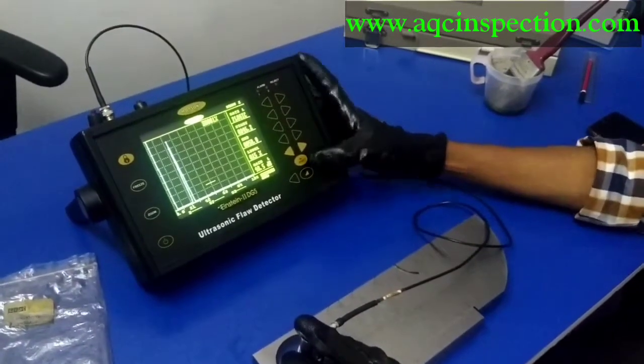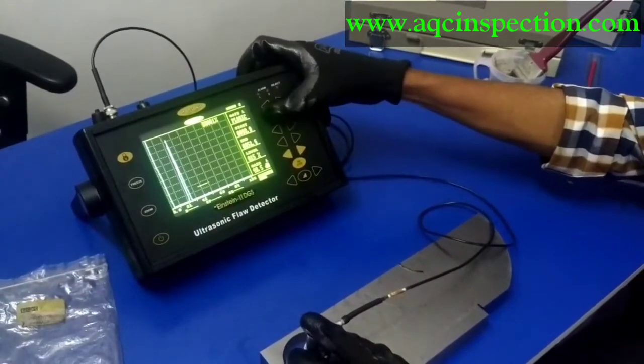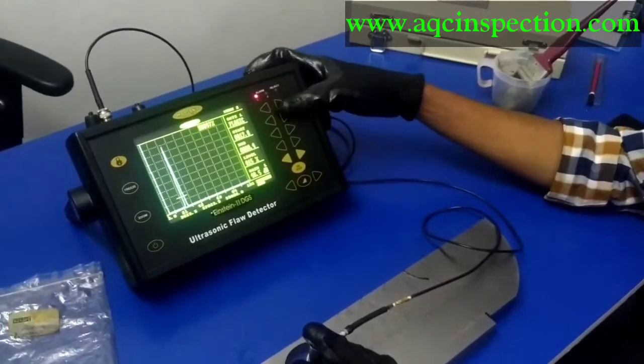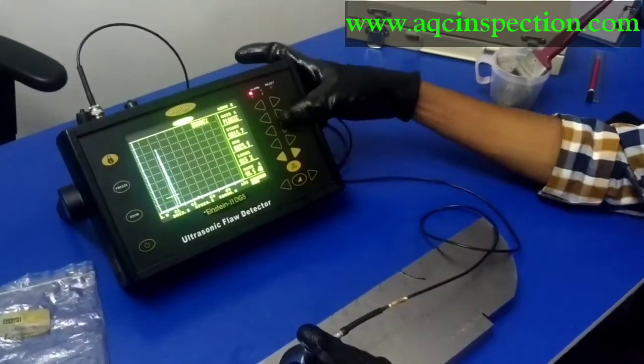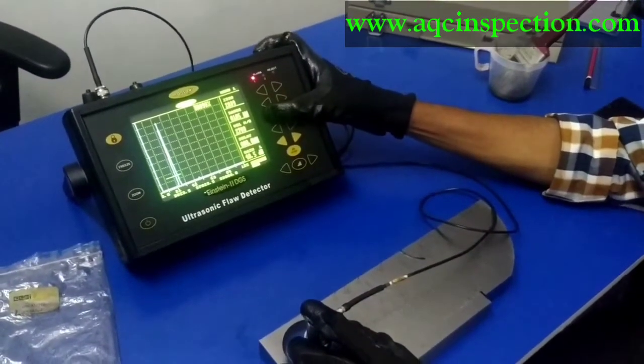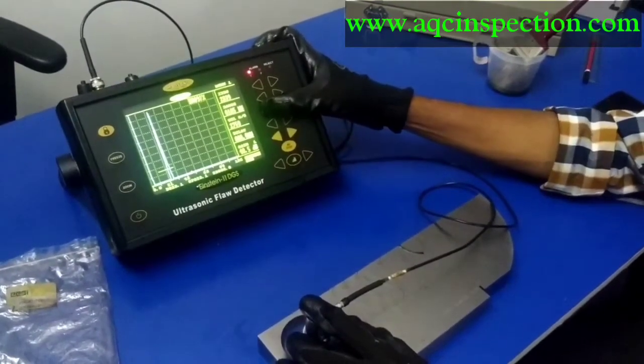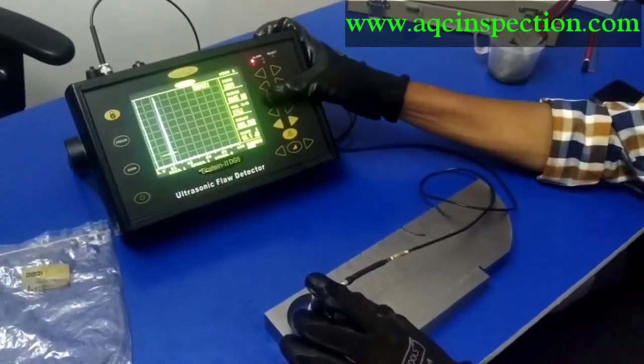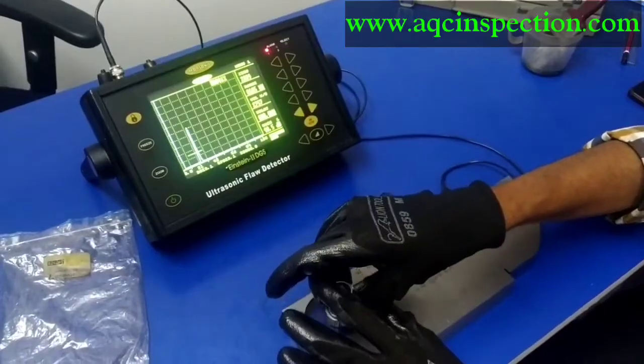Let me move my gate a little bit to the front. I am getting 23.5 mm. Let me see if you can adjust a little bit more. Let me go to the first menu and start adjusting my velocity once again. Yes. Right now I am getting 23.1 mm. This is absolutely fine. This is the velocity for this plexiglass. And there is also one more step.